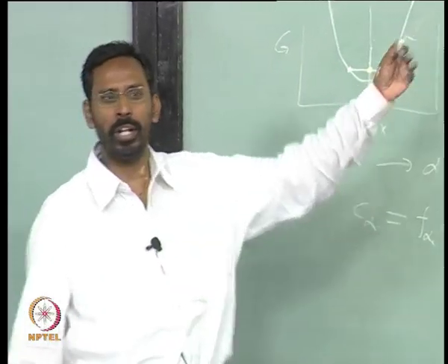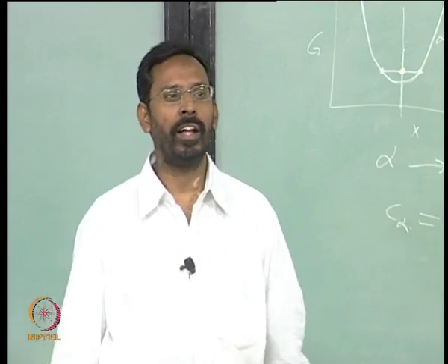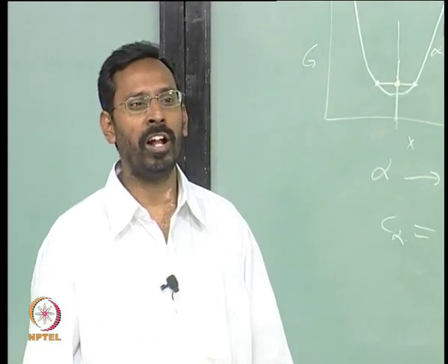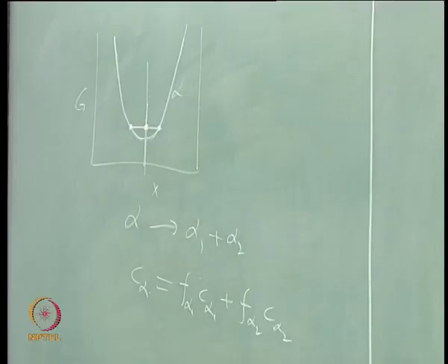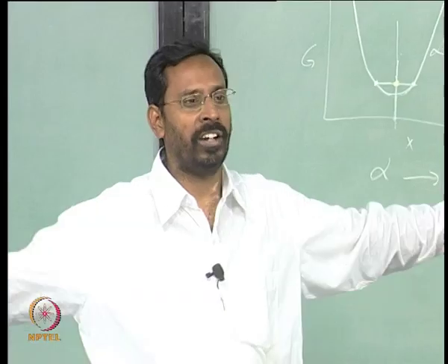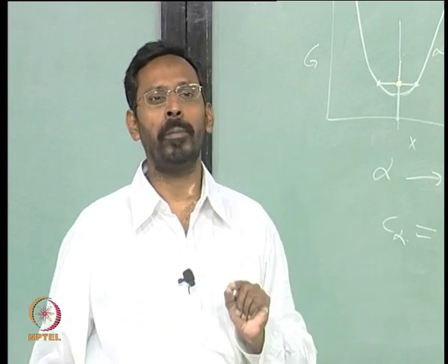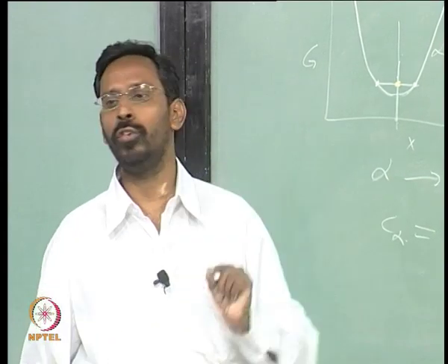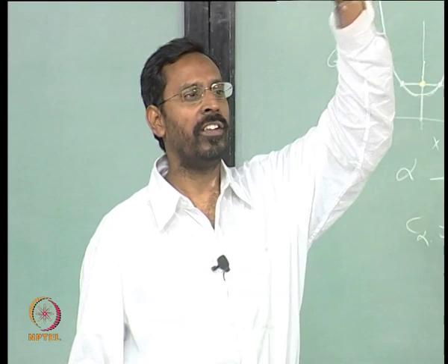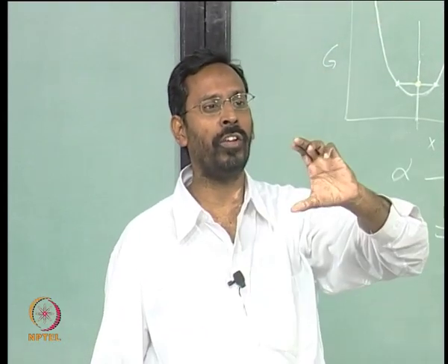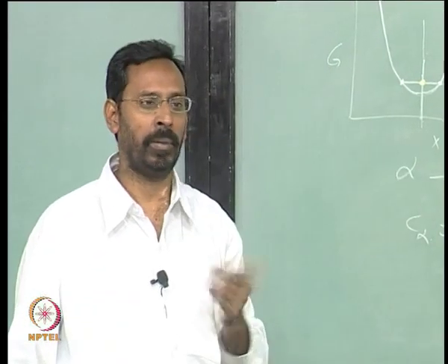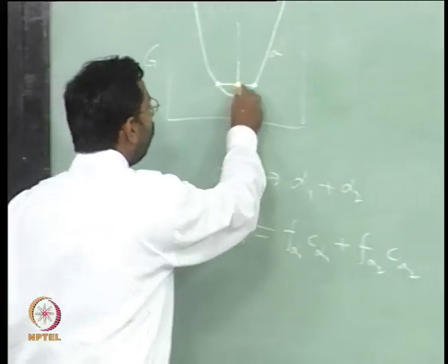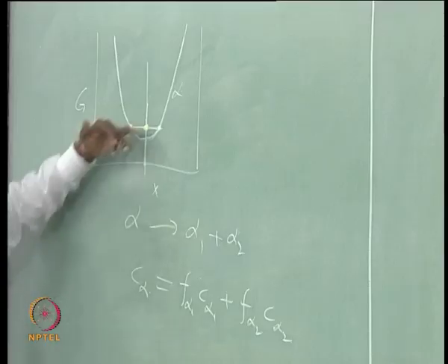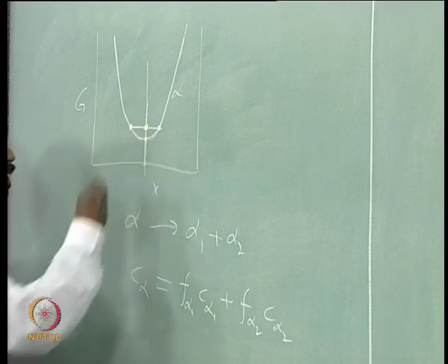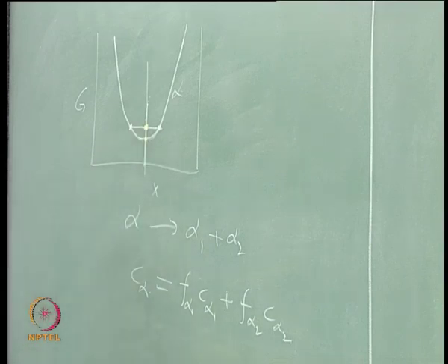That is what we have been showing in all the phase diagrams, even in the earlier case of precipitation, whenever an alpha phase splits into alpha plus theta. So, the alpha theta common tangent that we consider, and that particular point on the common tangent gives you the two phase free energy, and if the single phase free energy is higher than the two phase free energy, then only precipitation will take place. We have seen that. So, this is the free energy of this mixture, and this is higher than the free energy of a single phase.